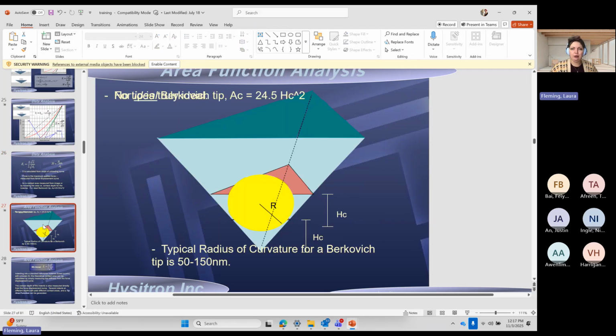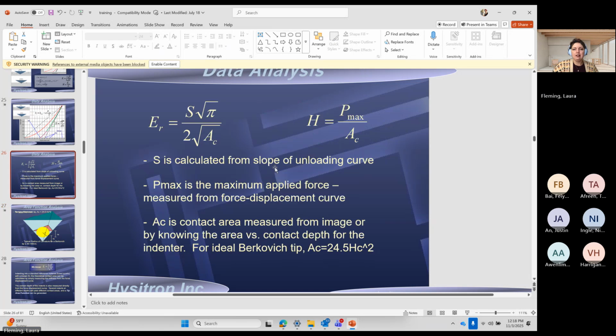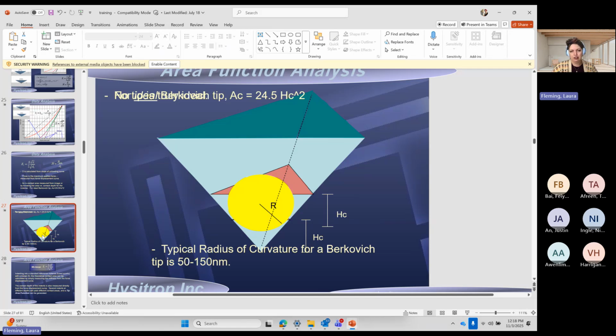However, we don't live in an ideal world. Of course not. It's nanoindentation. We're never going to be a perfect pyramid all the way down to the point. So there is some radius of curvature that occurs with any probe. And all of a sudden this idealized tip area function is no longer accurate, which means these results are no longer going to be accurate. So our hardness and reduced modulus results are only as good as our tip area function is.